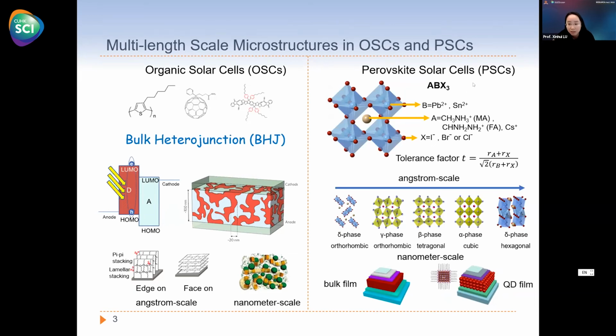And for perovskite solar cells, the crystal structures are well defined. Basically, all of them have this ABX3 chemical structure, and the BX6 octahedra share the corner and form this cubic cage, and then the A-site large cation inserts into this cage to stabilize this cubic structure. Depending on the ionic radius of ABX, the crystal structure can be cubic or distorted a little bit, become tetragonal phase, we call beta phase, or distort further, become orthorhombic, gamma phase. All these corner-sharing phases are black phases. And if there is further distortion, it can collapse into unwanted yellow phases. We call it delta phase. So these are atomic level or angstrom level microstructures we're interested in.